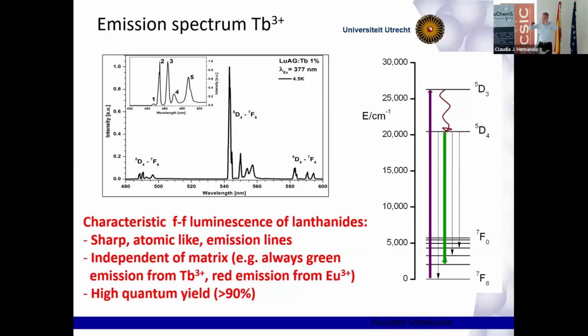The reason is again the same. Those energy levels arise from interactions between those 8 4f electrons in this inner shell, shielded by the 5s and the 5p, no interaction with the environment, so it doesn't matter whether it's an oxide or a nitride or a fluoride. Very different from the transition metals. You may know that chromium 3+ in ruby gives a red color. Chromium 3+ in many other compounds, like beryllium aluminum oxide, gives a green color. Depending on the host, the crystal field splitting changes and the optical properties, everything changes. Not for the lanthanides. This energy level scheme is always the same because it arises from this well-shielded inner 4f shell.